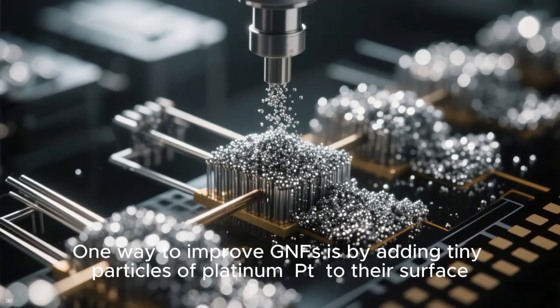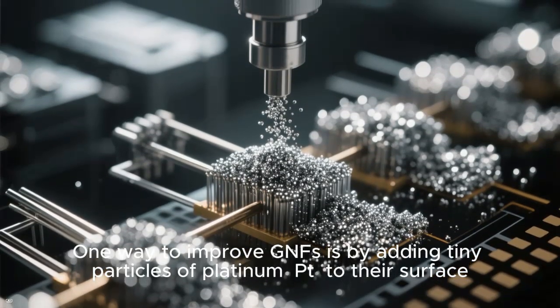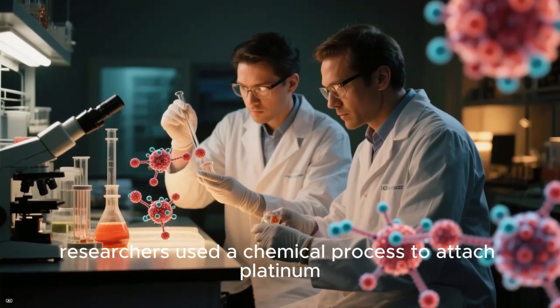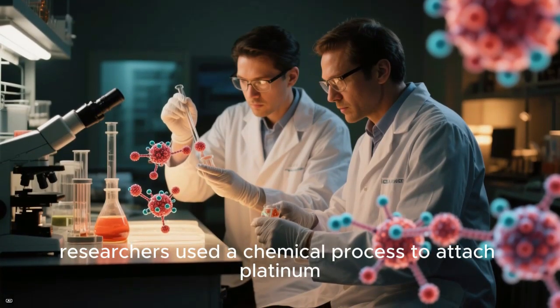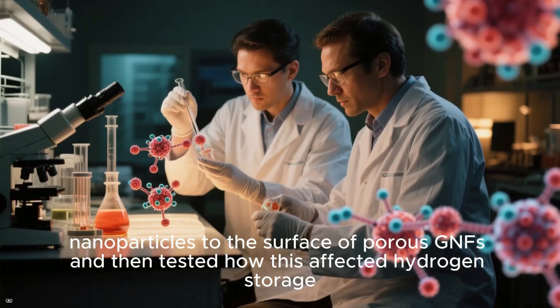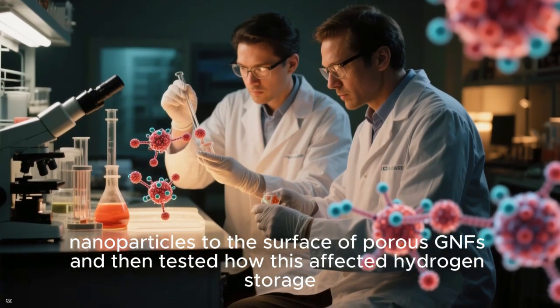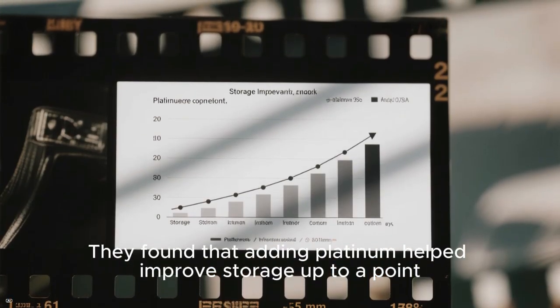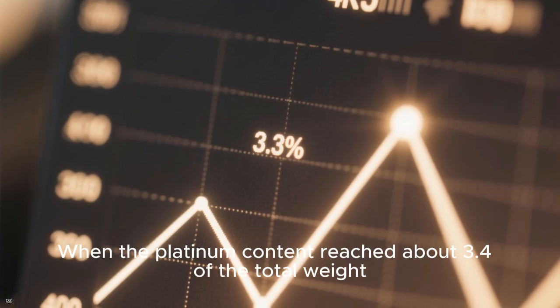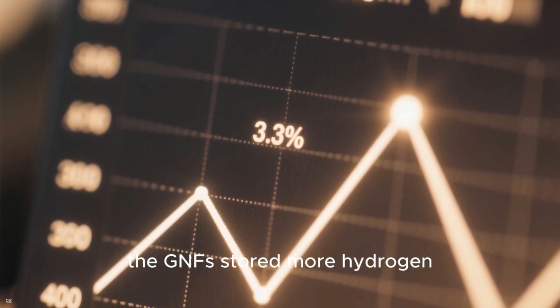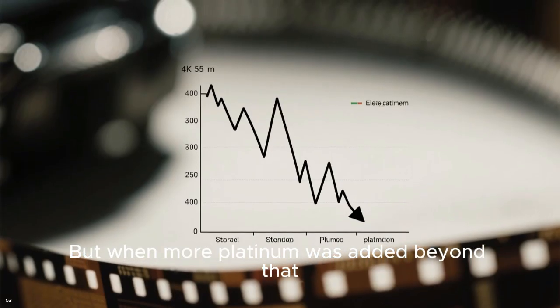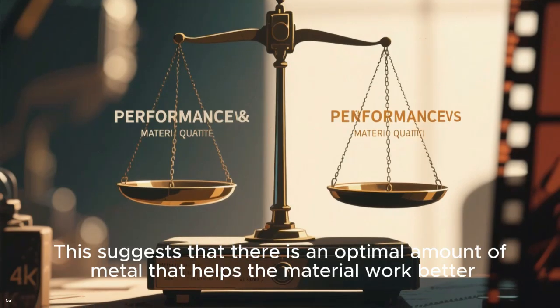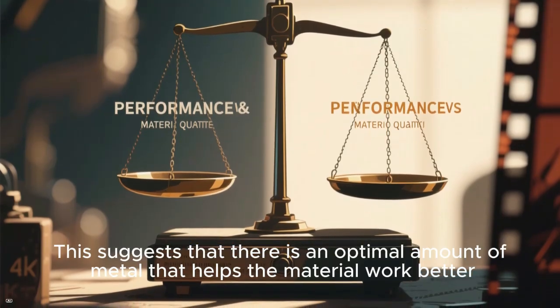One way to improve GNFs is by adding tiny particles of platinum, Pt, to their surface. In one study, researchers used a chemical process to attach platinum nanoparticles to the surface of porous GNFs and then tested how this affected hydrogen storage. They found that adding platinum helped improve storage up to a point. When the platinum content reached about 3.4% of the total weight, the GNFs stored more hydrogen. But when more platinum was added beyond that, the storage capacity started to drop. This suggests that there is an optimal amount of metal that helps the material work better, and going beyond that can actually reduce its performance.